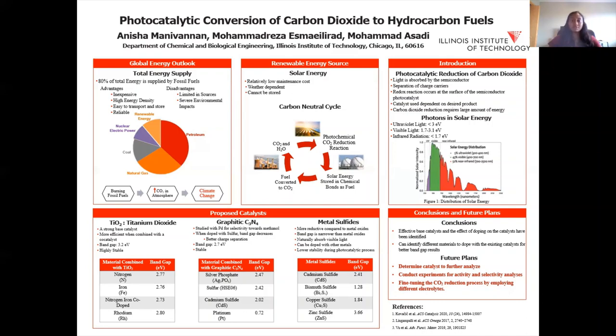Metal sulfides are useful because the conduction band has d orbitals of transition metals, which is very reductive compared to metal oxides. The valence band is made of three p orbitals of the sulfur atoms, which is less positive than oxygen atoms. So the band gap of semiconductors made of sulfur are narrower than metal oxides, and they naturally absorb visible light. One drawback is that it has a lower stability during the photocatalytic process.